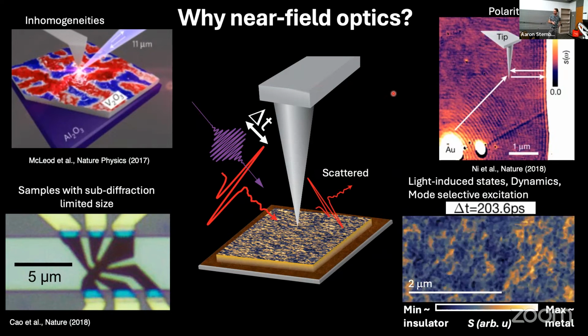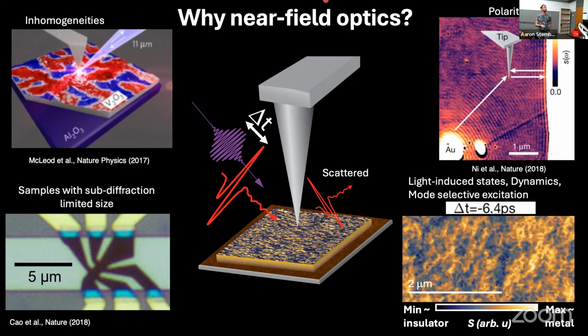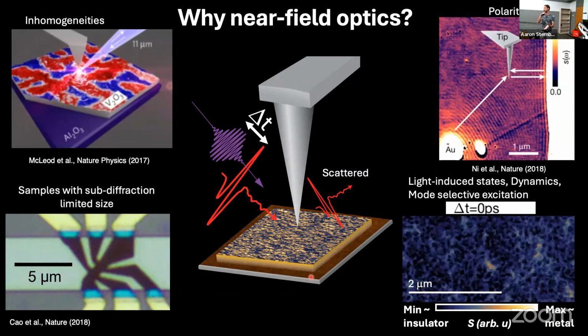Usually when you have the wavelength really large, it's hard to get it coupled. What accounts for the strong coupling to the tip? Okay, so this is a fantastic question, and maybe I'll allude to this, and I have one slide at the end talking about what we're pursuing here at UMD. So the tip is an antenna. And this antenna can be much larger than the wavelength of light, which is the mode we typically operate in the mid-infrared, in which case you can be in a quasi-static limit and still get enough signal in your scattered channel and be happy. The dynamic range suffers as you go to even longer wavelengths in the terahertz, and so people do try to use antennas that are resonant with the terahertz light to enhance the local fields, and that creates various complications and makes those measurements kind of difficult. But as long as the signal is large enough, basically if you have enough light coming in and your detectors on the other side are sensitive enough, then you can just use very long antennas and you're okay.